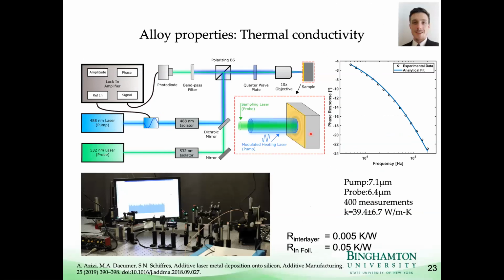So here's the raw results from this technique for a single point. This is the phase difference between the heating and the temperature response versus frequency. And then we fit this, the black dots are the data, and the blue curve is a fit to an analytical model. And so we found that the thermal conductivity of this tin silver titanium alloy was about 40 watts per meter Kelvin. So that's about half of what tin is by itself. So we think we can improve this a bit. But even still, because we can print a very thin layer of it, we can basically have an interface resistance that's about an order of magnitude smaller than conventional indium foil, which is already a quite good thermal interface material.